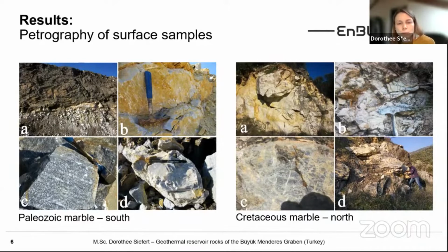And on the left, we see the Paleozoic marble samples or parts of them from the southern outcrop. And the main marble horizon is quite massive, has a fine to medium grain size and mostly evenly distributed grain size, but partly elongated calcite grains. The accessory pyrite explains the sulfuric odor while crushing the rocks, and typical for this marble is the light bluish gray color and a very low light transmission. And the marble is cross-cut by fine carbonate fissures, covered sometimes with iron oxides.